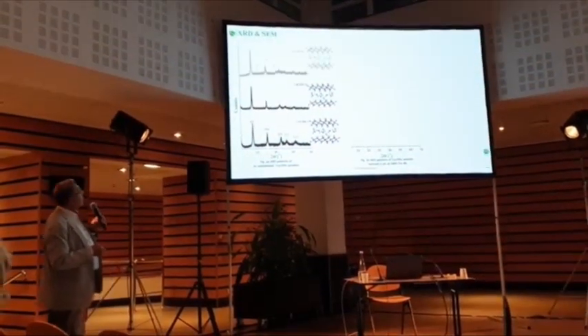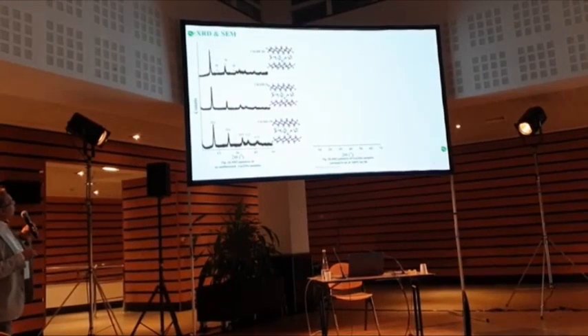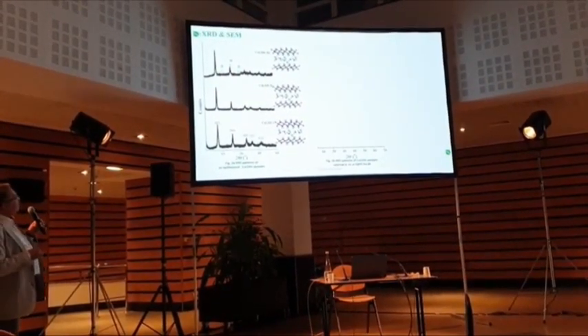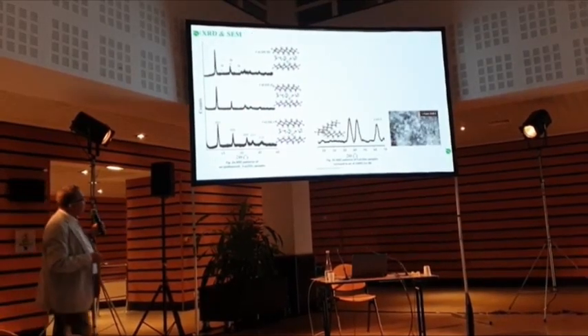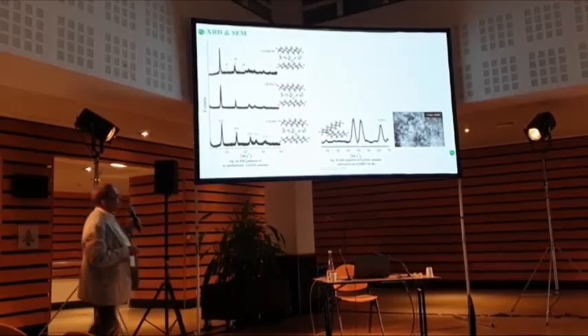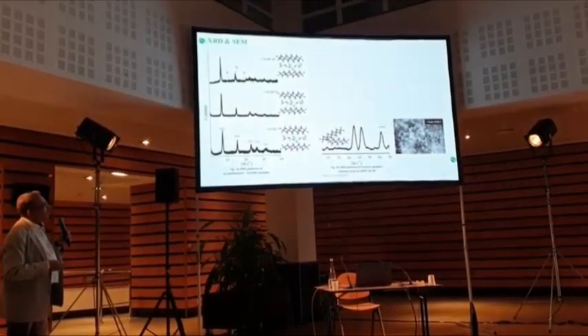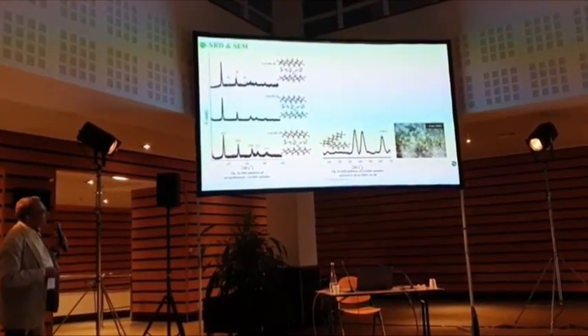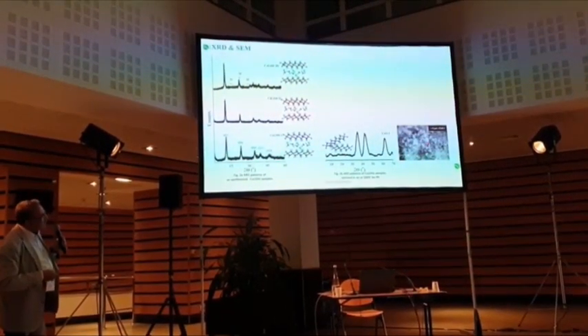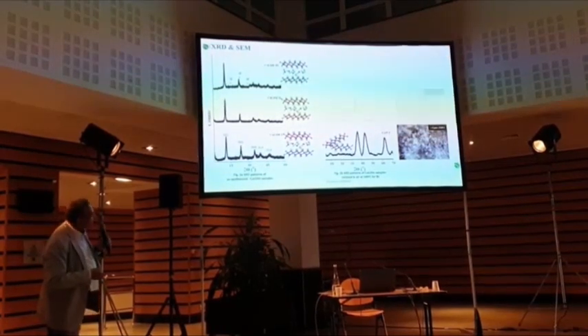Just by increasing the copper content, we keep the same structure, but we start to have some impurities from the malachite phase. Calcination of such material led to the collapse of the structure, obtaining copper oxide and magnesium oxide, replacing the structure with an amorphous-like structure of aluminum oxide. This is the same image of the material after calcination.